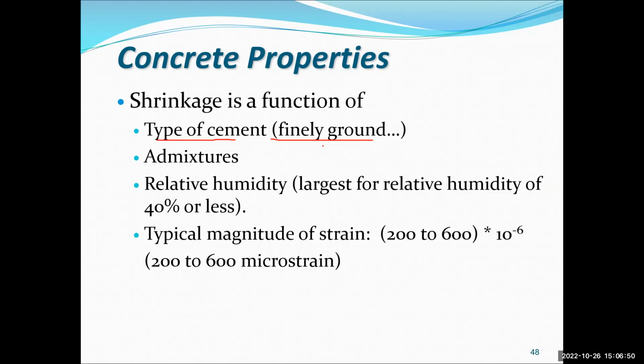That's why the cement is a major factor in the shrinkage. The admixture that we use is also a major factor, especially if you use superplasticizer. Superplasticizer reduces the water demand. And of course, if you reduce water demand, that means you reduce the amount of water, and that means it will reduce the shrinkage. Typically the strain due to shrinkage is between 200 to 600 microstrain. So that's a big amount.